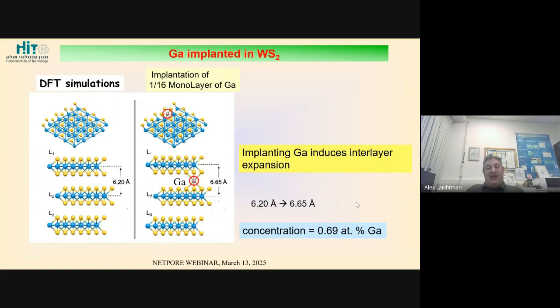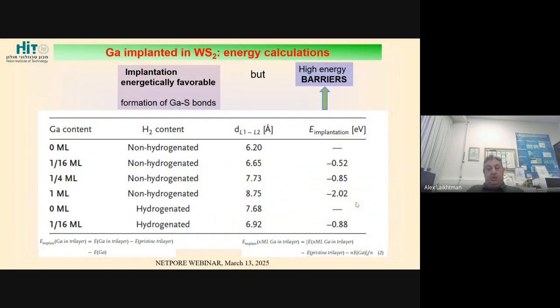This requires a lot of energy because, though implantation is energetically favorable, there is a very high energy barrier to overcome in the case of non-hydrogenated nanoparticles, because we need to expand the interlayer distance. In the case of hydrogenated or previously hydrogenated nanoparticles, we already have this expansion, either because of just adsorption or because of intercalation of hydrogen.